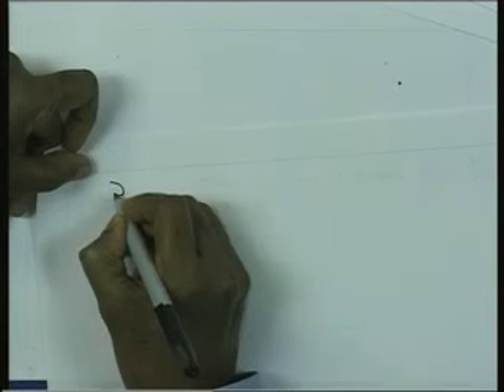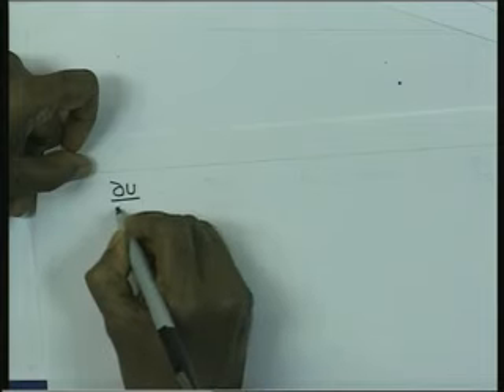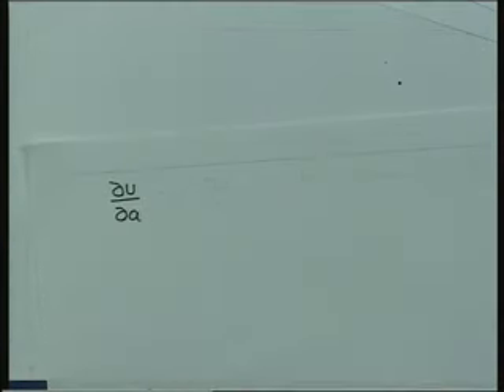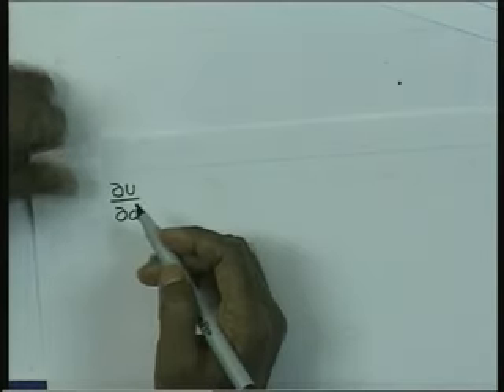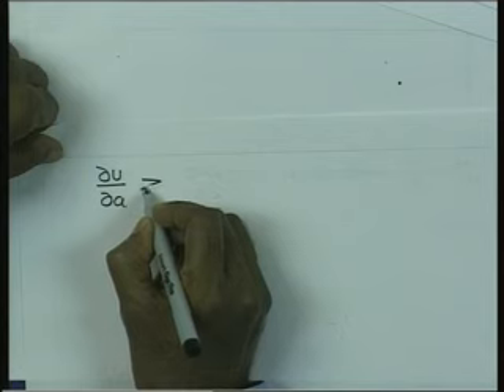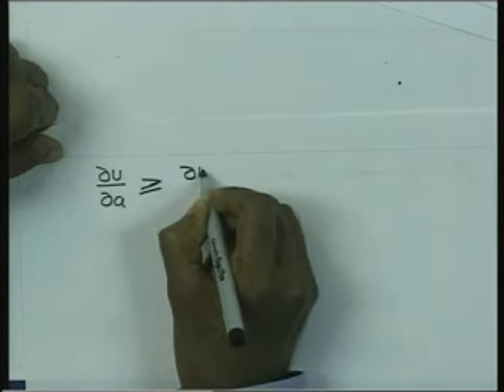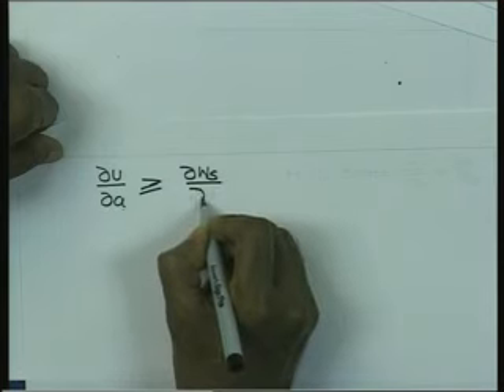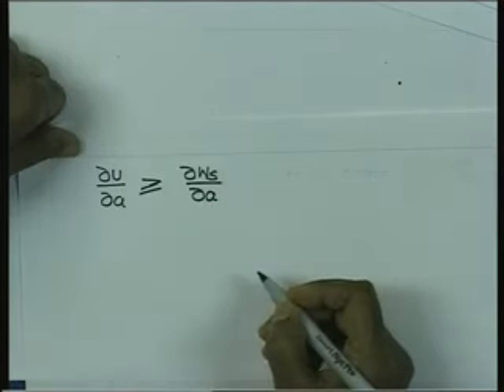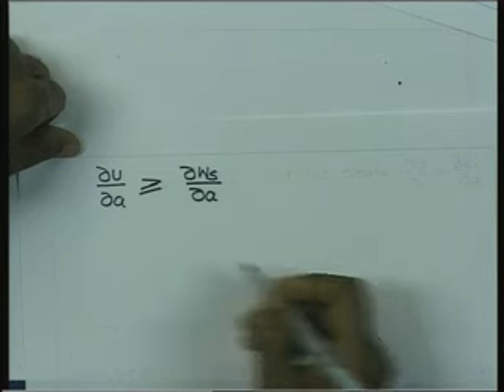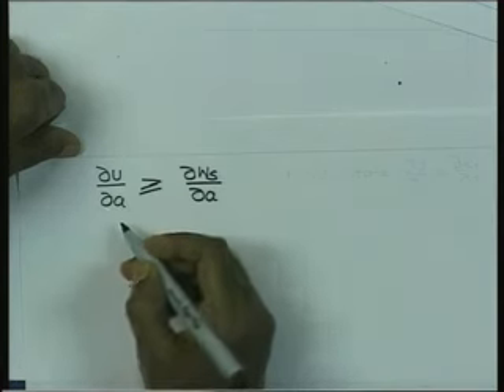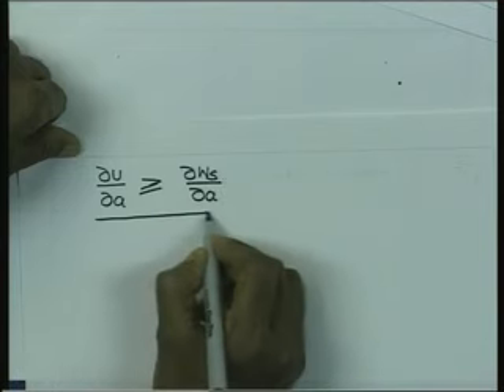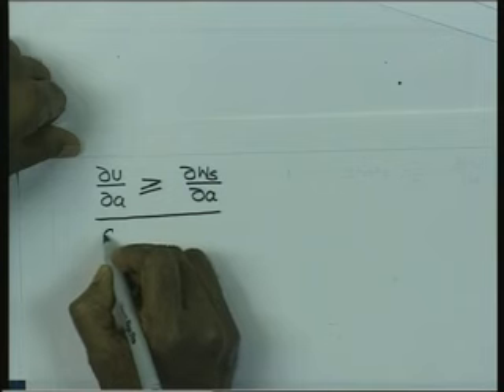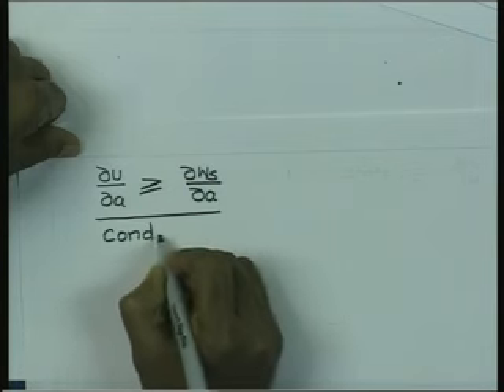So, we can write now the condition for the unstable crack extension, that delta U by delta A, which is the rate of release of strain energy, should be greater than or equal to the rate of absorption of surface energy, that is delta Ws by delta A. So, rate of release of strain energy greater than or equal to the rate of absorption of surface energy. This is the condition of unstable crack extension.